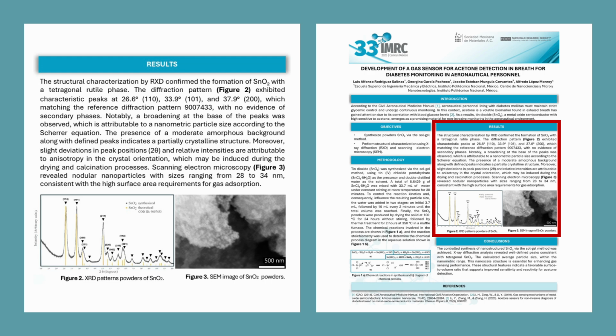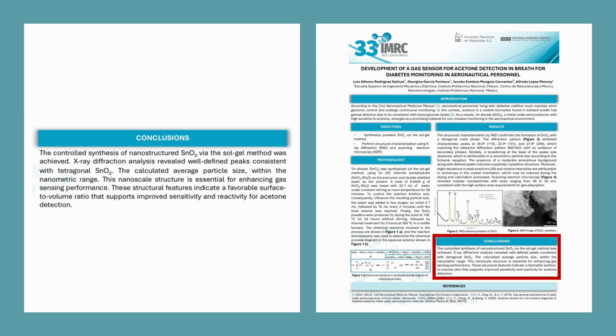Furthermore, scanning electron microscopy, presented in Figure 3, reveals nodular nanoparticles with sizes ranging from 28 to 34 nanometers. This nanoscale structure is essential because it provides a high surface area, which is crucial for gas adsorption and therefore for sensing acetone efficiency.